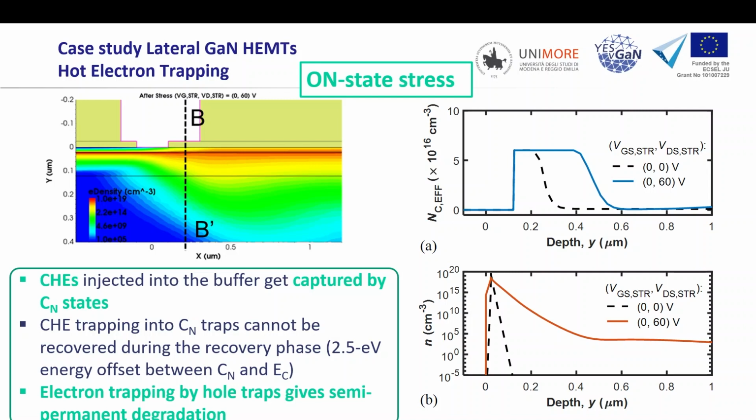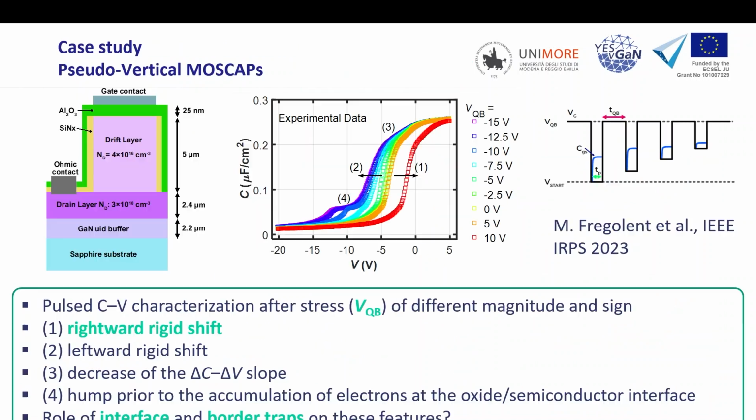And we also performed some UV light experiments to see if we could recover this easily, and to a very high extent we basically recovered the whole of this permanent damage. So that also pointed to the fact that it was traps and not another kind of degradation mechanism.